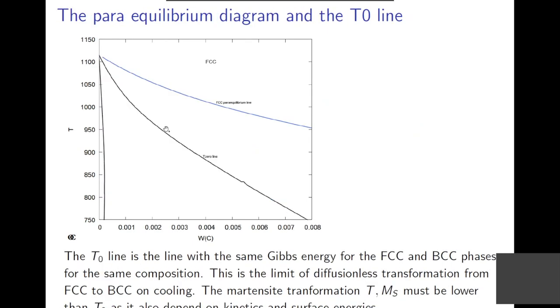Then Hari Bhadeshia talked about the T0 line, and you can easily calculate where you have the T0 line, where you have the same Gibbs energy for FCC and BCC with the same carbon and manganese content. And this determines quite a lot of the possible transformations which are non-equilibrium in the system.